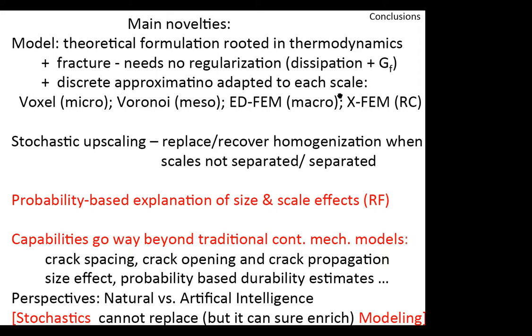So basically, another ingredient was that we chose discrete approximation, which is adapted to each and every scale. At the microscale, those were your voxels. This is modeling of the cement. At the mesoscale, those are your Voronoi cells. At the macro scale, this is embedded discontinuity finite element. At the XM macro scale, this is reinforced concrete with the X-FEM representation. So if you look into the literature on discrete approximation, you will find that this covers the whole set of discrete approximations. I don't think there's any more, if you want to think of that. And basically, we use each and every one to play an appropriate role.